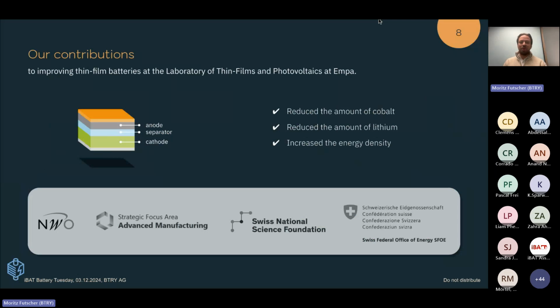So in this part of the talk, I first want to highlight some contributions we have been working on at Empa in the Laboratory for Thin Films and Photovoltaics to bring some additional improvements to this thin film battery field. I especially want to highlight three different works. One was how we reduced the amount of cobalt by switching the cathode from an LCO to an NMC811 cathode. How we were able to reduce the amount of lithium by developing an anode-free thin film solid-state battery. And then how we can increase the energy density by stacking these thin film cells on top of each other. The work from Empa was funded by different funding agencies, which I mention here below.